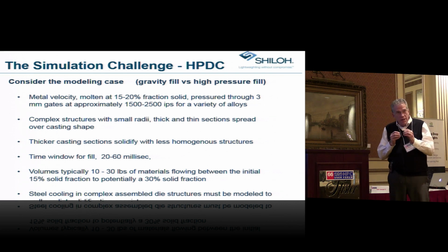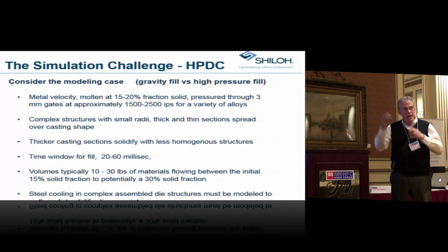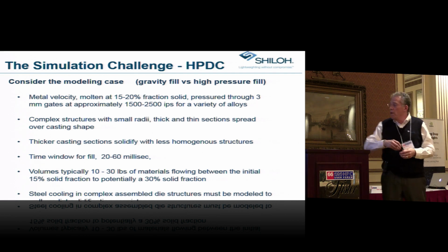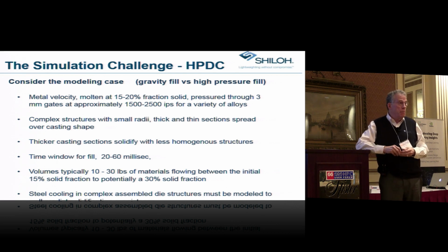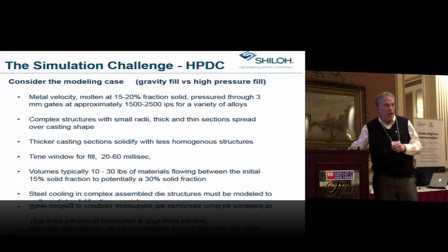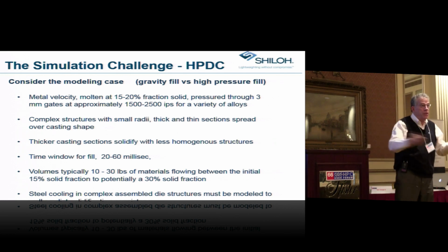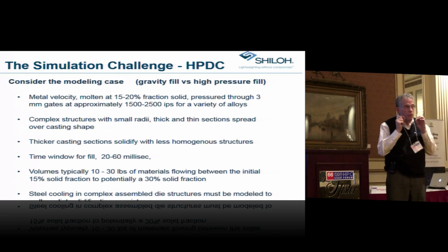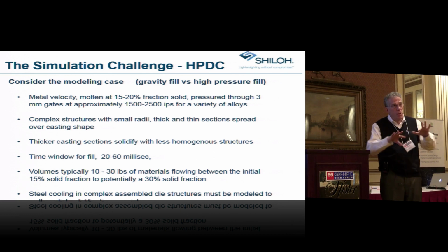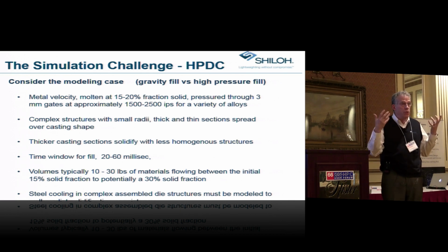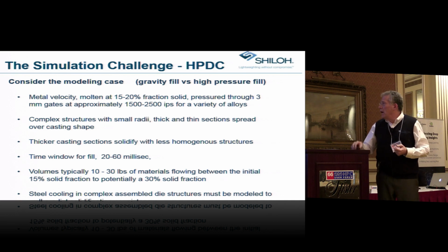You have thick sections and thin sections, and they moderate over the part. You have a fill window that's 20 or 60 milliseconds in that range. So if we think about that violent feed, it's filled, it's done. It's already over, and we're having to predict the way that could be 20 pounds or 30 pounds of material moving through the die in that 20 milliseconds. That's part of why the HPDC is important to us.